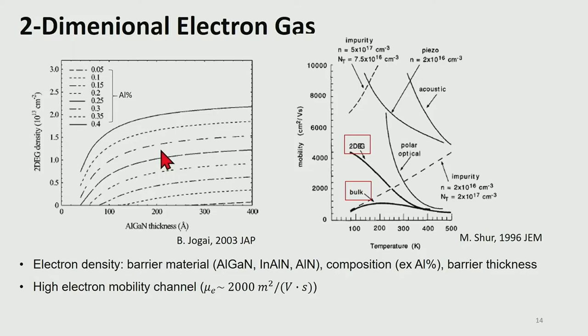In addition to the high electron density, the electron mobility is also quite high. In the gallium nitride, if you see this right figure, the gallium nitride bulk mobility is mainly limited by the impurity scattering. But in the case of the 2DEG channel, thanks to the separation between the donor states and the 2DEG channel, the impurity scattering is much less. So the electron mobility can be as high as about 2,000 at room temperature.